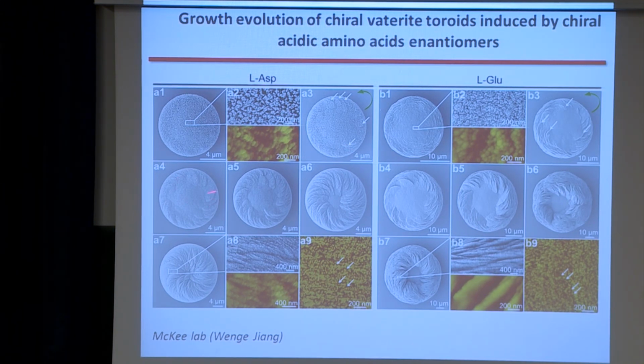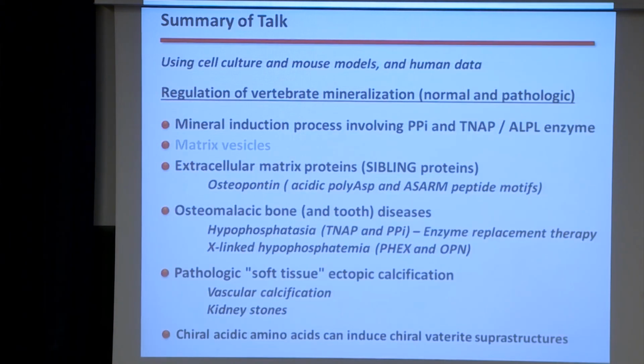The platelets enlarge, they grow on top of each other, they encroach upon the central core, and in the case of Asp, they fill it right up to the middle. All nanoparticle organization and roughness, and here with the Glu. So chiral amino acids can induce chiral biomineral structures. And we're very excited about that.